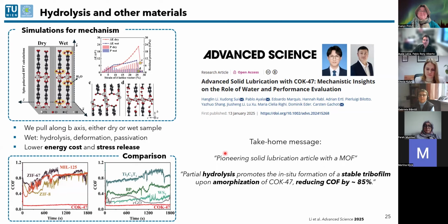additives. And second, that we shed some light on the mechanism. So here, what we saw was this hydrolysis that promotes an in situ formation of a stable tribofilm. And this happened upon amorphization of COK-47. And this tribofilm was responsible for reducing the coefficient of friction by almost 85%.